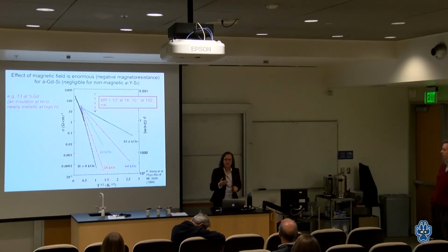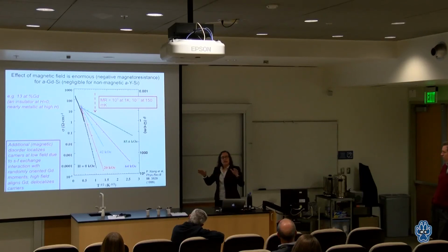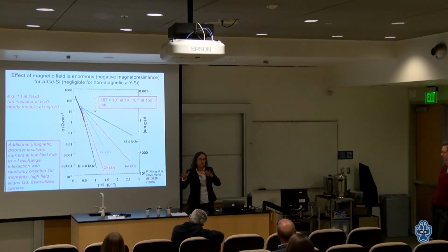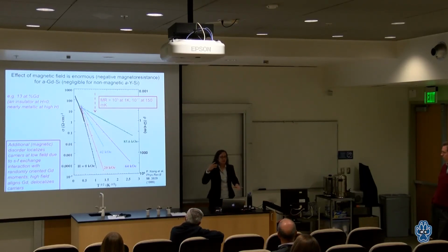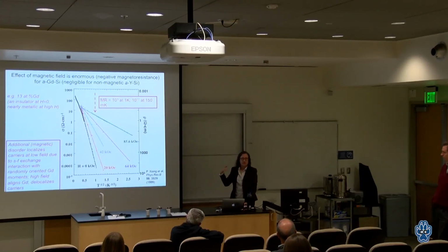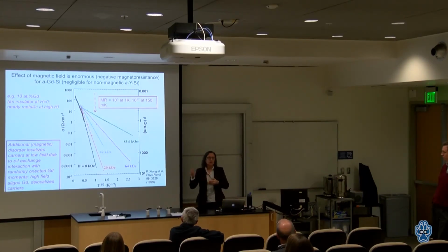If this were a simple metal, additional disorder would be a scattering center. So the mean free path would get shorter, and the mean free path getting shorter would make the resistivity increase. Now line those up, so the disorder decreases, I don't scatter as much, so the mean free path gets longer. That would be a negative magnetoresistance. The problem with that model is none of these materials are in a limit where you can be talking about a mean-free path. They're all in this metal insulator transition, where what's really going on is Anderson localization. So you have to do the Anderson localization with their different potentials. It's not a scattering center in the sense of a mean-free path. It's a scattering center in the sense of trying to localize the electrons.